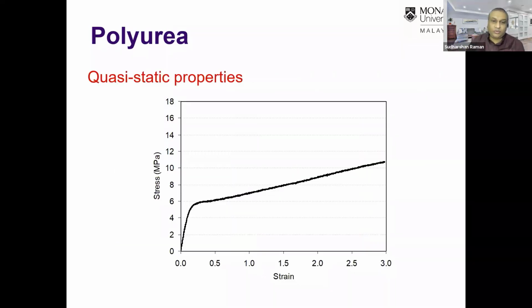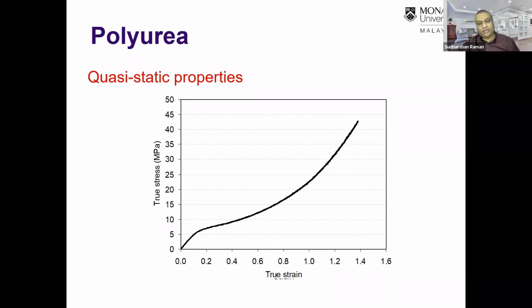Based on the testing, we tested it at quasi-static condition as well as various strain rates. This is the quasi-static properties, the engineering stress strain curve of the polymer, where the strain can go up to close to 300%, the highest strain recorded being 2.98. And then when we tested it at different higher strain rates, this is the true stress strain curve of the same material in the quasi-static condition.